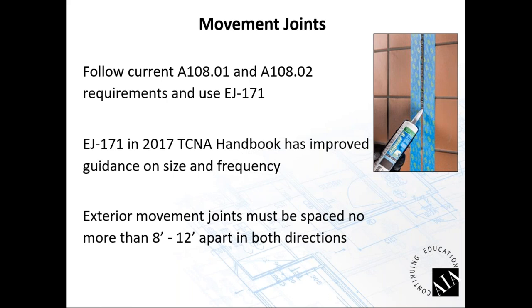Use requirements from TCNA EJ 171. EJ 171 in the 2017 edition was improved, showing guidance on size and frequency. Exterior movement joints, I'll touch on this again, must be spaced between 8 to 12 feet apart in both directions. So addressing this, and remember, as the architect, it's your responsibility to lay out these movement joints, making sure that they're being placed in the proper application so that we don't have a problem, and that the proper material is being used for the movement joints, backer rods being put into place, the proper siliconized caulking that's going to move in conjunction with this system.